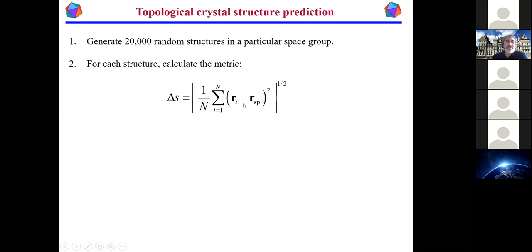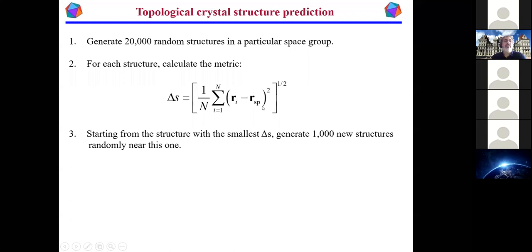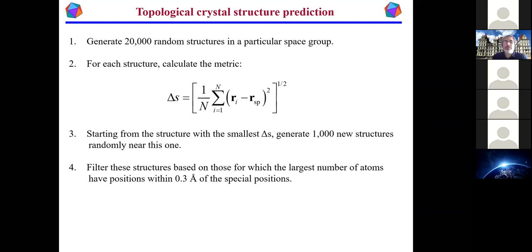And of course, not all of them can be freely varied this way because there are constraints due to the geometry of the molecule, right? You have to satisfy the bond constraints and all of that. But among the degrees of freedom that you have, you can try to match the positions to these special positions in the unit cell. So you're looking to minimize this little distance metric. Okay, so you can evolve a set of random structures, try to find those with the smallest delta S, generate some new structures, let's say around the one with the smallest delta S, and then go from there, right? And you just keep going until you find the smallest value of this delta S that you possibly can.